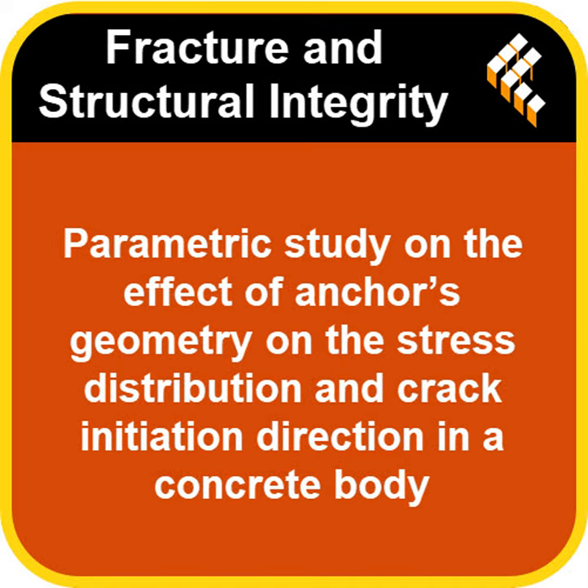So summing it all up, the big takeaway regarding anchor shape and concrete failure is that the anchor's geometry isn't just incidental. Its depth, and to some extent its width, if it's deep, directly affects how stress spreads out in the concrete. And that, in turn, dictates the likely shape and angle of that brittle cone failure if you pull hard enough. And the trend is deeper is better, and wider, if it's already deep, is also generally better for promoting a flatter, potentially more resistant failure.